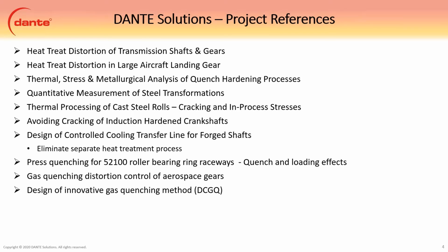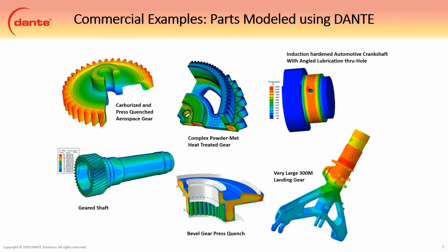We've looked at normalizing processes to improve them, bearing rings, gas quenching distortion of aerospace gears. And the last one is we actually recently designed an innovative gas quenching method that we've tagged Dante Controlled Gas Quenching, that actually controls the temperature of the incoming gas to control the phase transformation gradients. And it's a great means to reduce shape distortion. So the actual non-uniform transformations that occur during gas quenching. You can't get rid of the size change from going to martensite, but you can get rid of shape change.